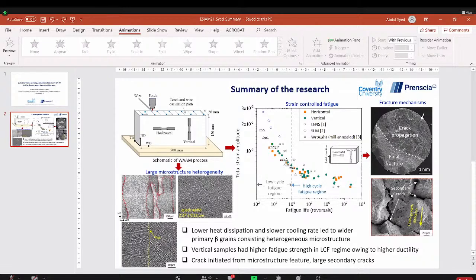Yeah, that's a good question, Jawad. We actually did a parallel program to understand the residual stress behavior when we remove the wall from the substrate, and also after extracting some dog bone samples and some compact tension coupons for the fatigue crack growth testing. We observed that after extracting these very small samples, around 10 millimeters in diameter, compared to the size of the wall, which is 500 millimeters, there are very low residual stresses, which are very close to any technique's resolution. For example, around 10-15 megapascals overall.